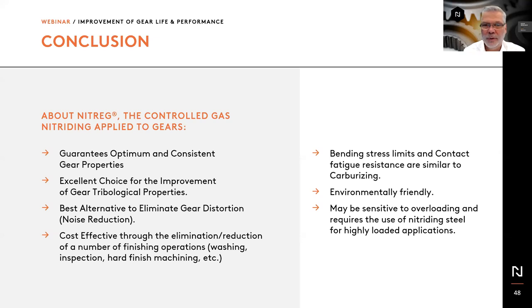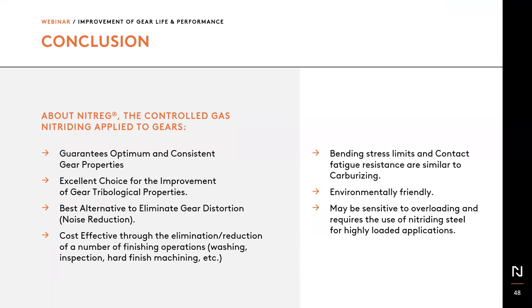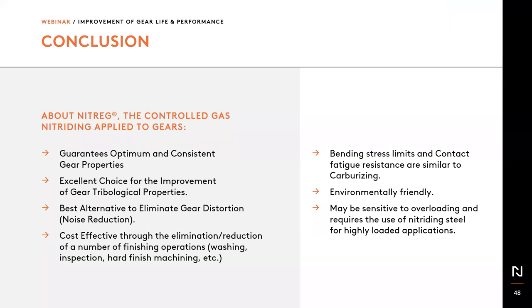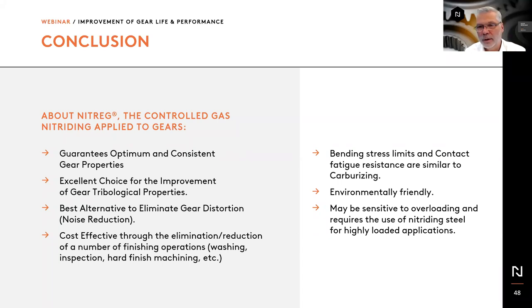So we do perform both processes, and we see advantages in one or the other. Now, what can definitely be said about nitriding is that it guarantees very good tribological properties, and it does eliminate gear distortion. For several gears and types of gears, it is cheaper when you think of the cost and iterations involved in quench press, for instance, and the cost of final machining or rough machining or gauging components which are manufactured in high volume.